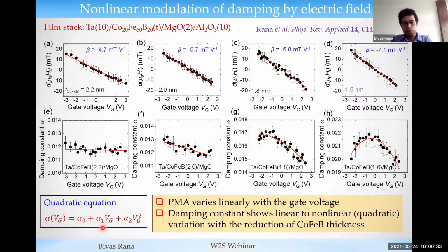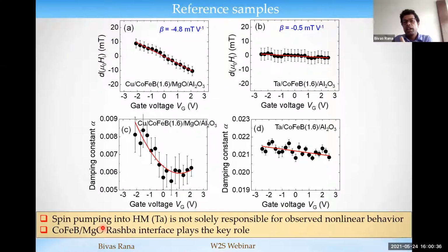Now, what is the origin of this nonlinear variation? Before going to that, I'm showing some more results measured from a reference sample, where we replace the heavy metal layer, the tantalum, by the light metal copper, so that we do not have a loss of spin angular momentum by spin pumping. Then we also observe this nonlinear variation of the damping constant, and that means we concluded that maybe the spin pumping into the heavy metal is not solely responsible for the observed nonlinear behavior.